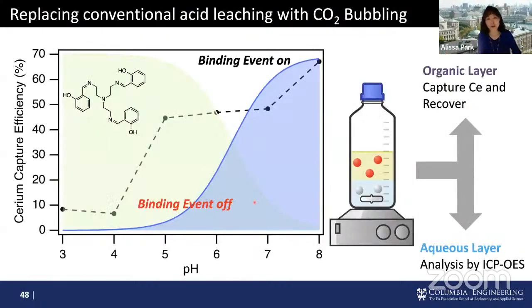Another important thing is that this system will be catch and release, catch and release. Again, we need to regenerate and release that cerium, or rare earth elements, back out. When we look at the binding on and off events, it's between pH 5 to 8. And this is a really great pH range, because we can simply capture cerium or other target metals, and then by bubbling CO2, we can release the cerium back out. And then by bubbling air, we can go back up and start to regenerate these structural ligand systems. And this is real green chemistry.